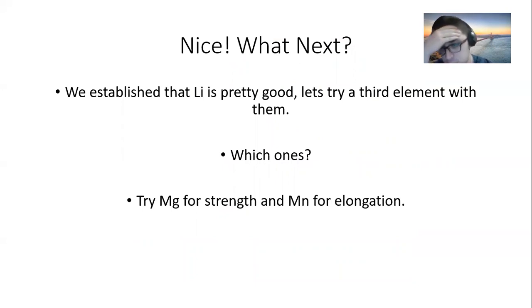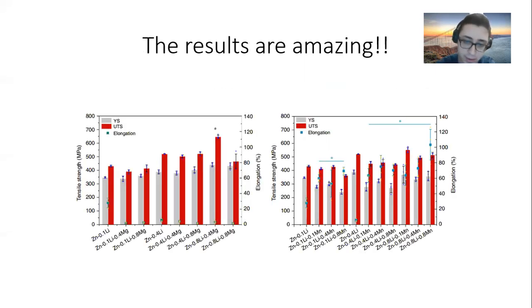So the researchers established that lithium was already good, so they decided to try a third element with lithium and zinc, but which ones? They decided to use magnesium for its strength and manganese for its elongation properties. And then the results were amazing, really. If you look here, hopefully you can see my mouse, this zinc 0.8 lithium, 0.4 magnesium has an ultimate tensile strength of almost 650 megapascals. That's a really good value considering that magnesium alloys can only get to 350.